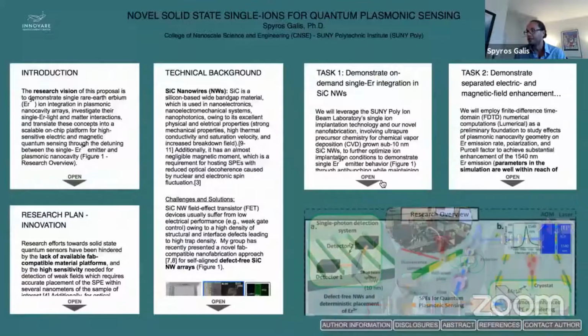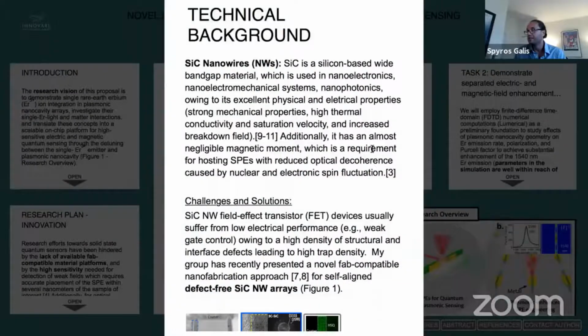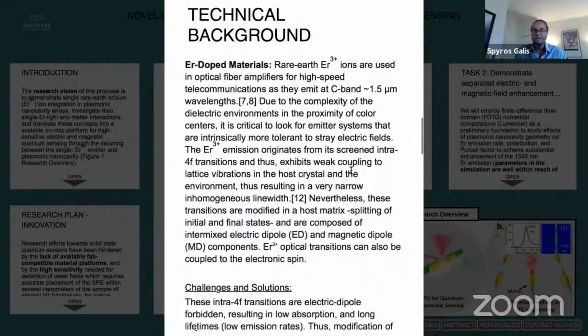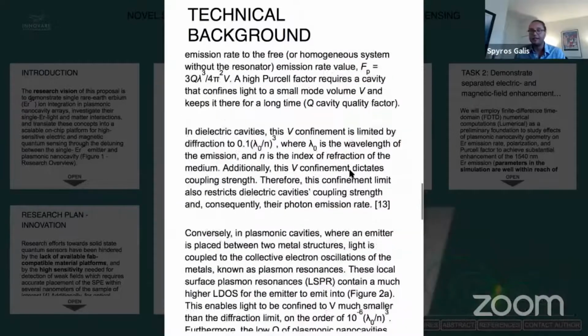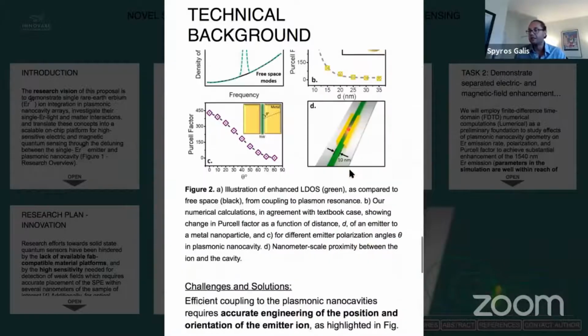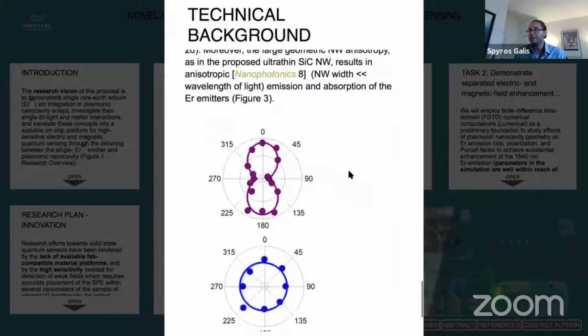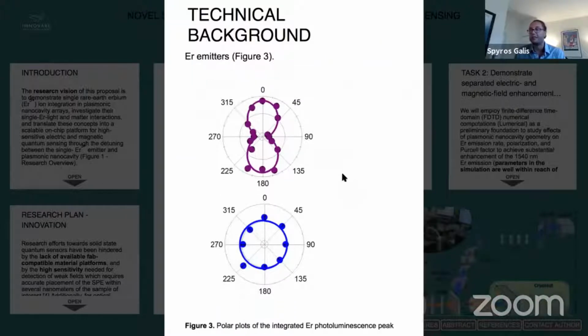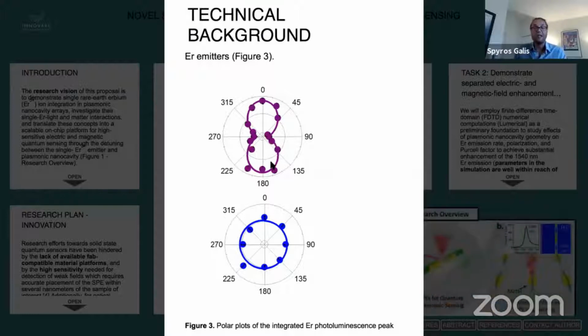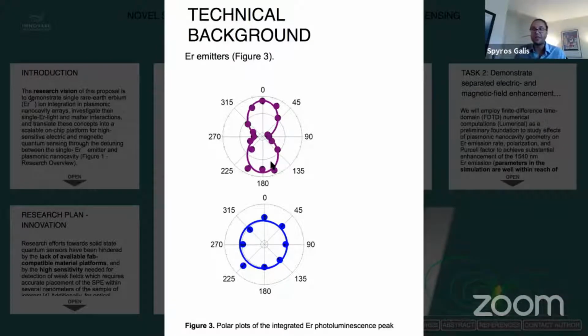Let me show you the next figure. This is presented in the last figure in this panel, where we have demonstrated preferential polarization emission from the nanowires, again, due to the anisotropic dimensionality of the nanowires, in contrast to the expected isotropic emission behavior when erbium ions are implanted in bulk thin films, which is the bottom part of this figure.